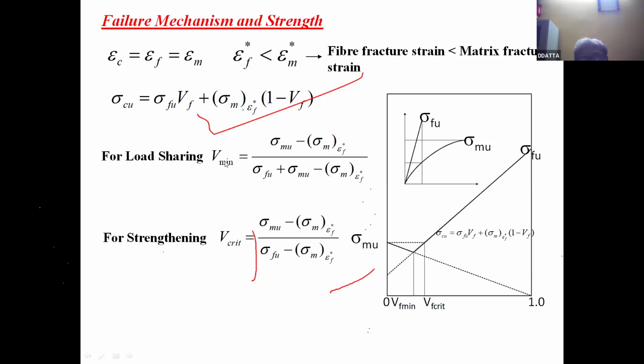So from this, we can derive a minimum fiber volume fraction, and also a critical fiber volume fraction. So there is a difference between the two. The difference is that if the volume fraction is below the fiber minimum, then effectively the load shared by the fiber is not effective. Whereas if the volume fraction is less than the critical volume fraction, the fiber is not strengthening the composite, as if it were made of the matrix alone, which could have worked well. But if we want to put some strengthening effect by the fiber, then the fiber volume fraction must be greater than the critical fiber volume fraction. That is the concept of these expressions.